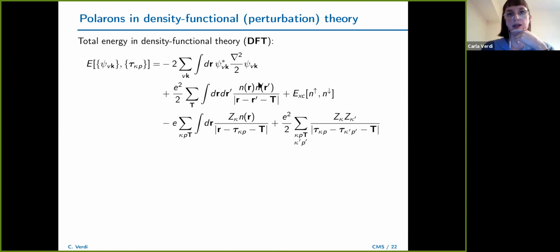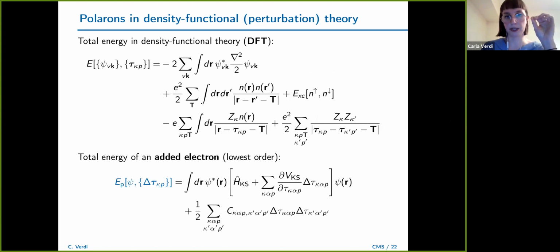One of the problems is the fact that the polaron self-localization and the energetics strongly depend on the exchange correlation functional. And the reason for this is mainly the so-called self-interaction. So when you add one electron in DFT, you're actually also including the interaction of the electron with itself, which is of course unphysical, and is one of the known problems of density functional theory. And there are various solutions for this, but this poses a serious problem for polaron calculations in DFT. So what we wanted to do was to find a rigorous formulation that didn't have this drawback.